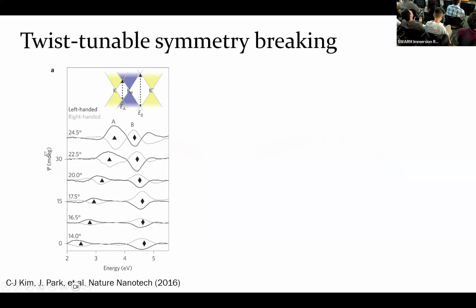what is plotted on the y-axis is the circular dichroism. That's basically the difference in optical reflectance of left and right-handed circularly polarized light. And different curves are different twist angles. So each black curve is basically the left-handed structure. Each gray curve is the right-handed structure, and you're seeing that they have opposite signs if you measure the circular dichroism. And if this is for a mirror symmetric structure with no handedness, then the signal will be zero.